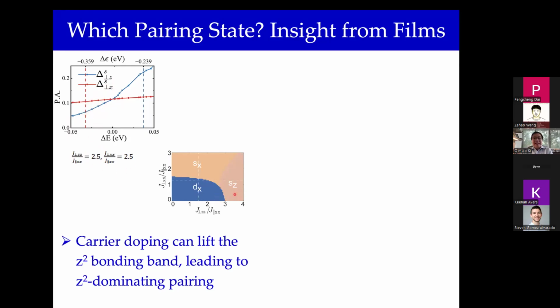We've chosen parameters that are sitting here. One could also study regimes where the D-wave pairing is dominant, and there's a somewhat related trend one could construct in response to the tuning of the level spacings between the z-square orbital and the x-square minus y-square orbital. So here we're focusing on this, and the important point is that these different orbital pairing amplitudes will be manifested in different variations of the gap on the Fermi surface.